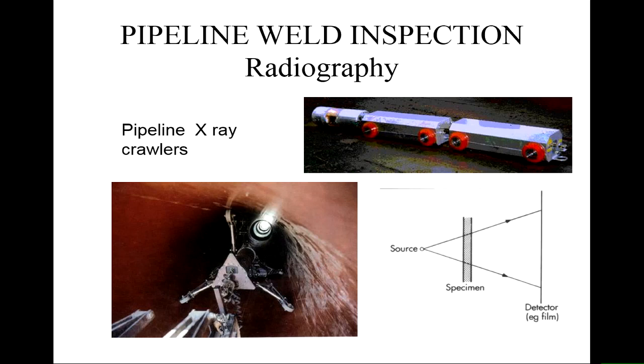So you put an X-ray source into the pipe generally, or as we'll see in a minute, on one side of the pipe, and then you actually put a film or a detector on the outside of the pipe or on the other side of the pipe, and you look for variations in X-ray intensity that makes it to the detector. And if the pipe is complete and there are no defects, there's a lot of material to absorb the X-rays. If there are holes and pores, there's less material to absorb the X-rays, so more X-rays will make it to the film. So on the film, things go dark generally when there's a defect present in the system.